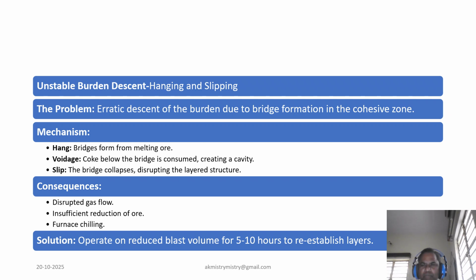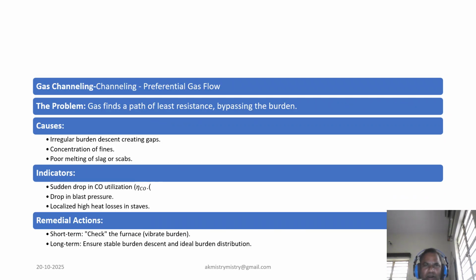Now, speaking of the gas flow, our next challenge is channeling. This is when the reducing gases, lazy by nature, find a path of least resistance and simply bypass the bulk of the burden. It's caused by gaps from irregular descent, concentration of fines, or poorly melting material. Operators spot it through key indicators: a sudden drop in CO utilization, a dip in blast pressure, and localized hotspots on the staves.